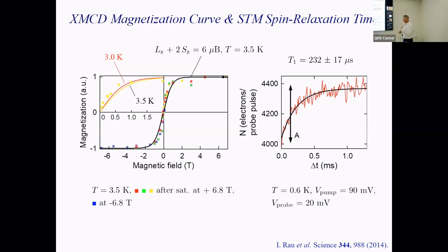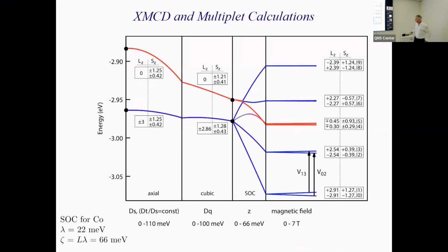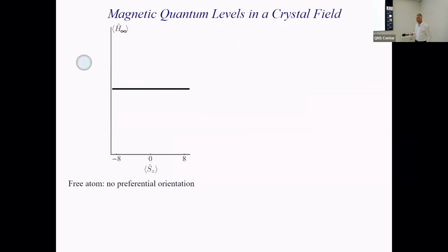So in principle, this is, again, a very fascinating system because it's the highest anisotropy that you can achieve in a single atom, because we have here a system that has preserved the orbital moment, which is otherwise only found in the gas phase. You cannot have more than 3 Bohr magnetons, and it has preserved roughly all the 3. So that's fascinating by itself. But there must be something else which gives the stability of these single atom magnets, and which was preventing us from finding their stability so far.